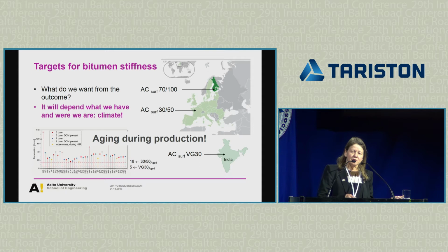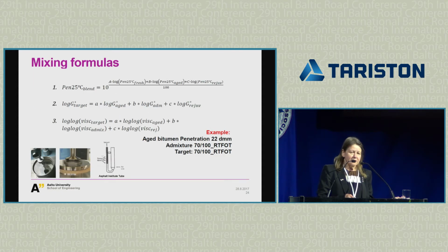And then comes this interesting question, should we take into account the aging during the production? How do we take it into account? Do we shoot for virgin materials or RTFOT aged materials? So then when we have selected the targets, comes the question, okay, what rejuvenator and how much? And we have, let's say, 3 different ways to do it, like mixing formulas based on these parameters, one based on penetration, then based on G-star, DSR, and then using viscosity.